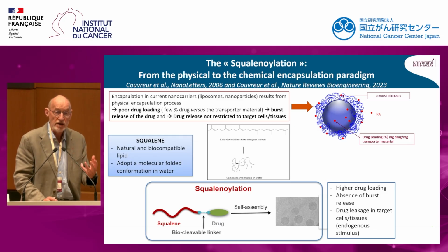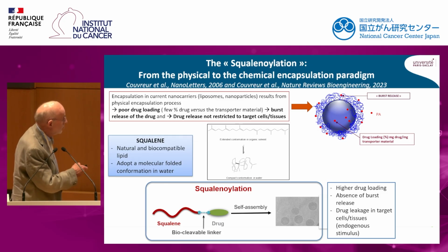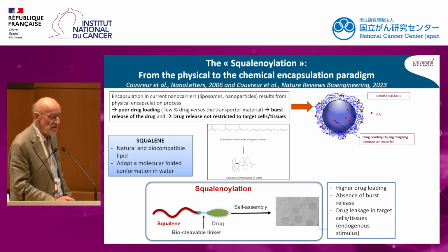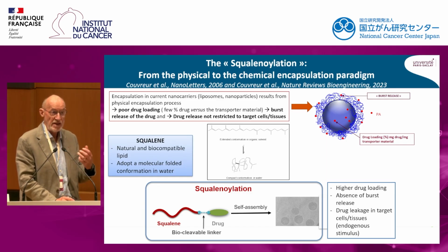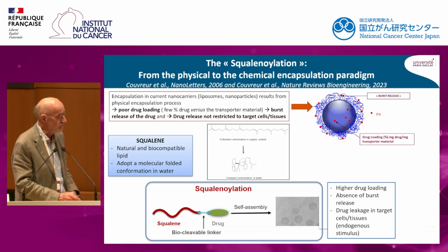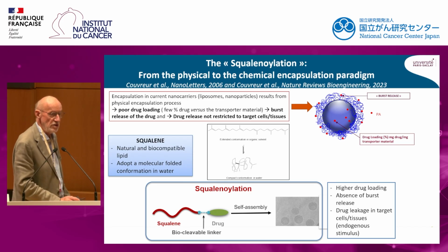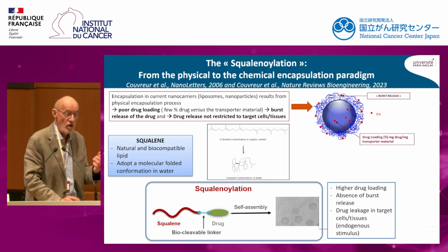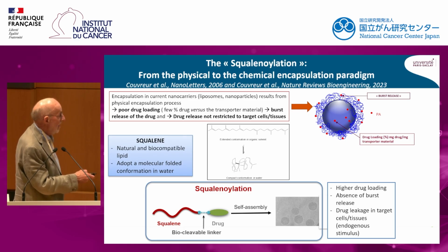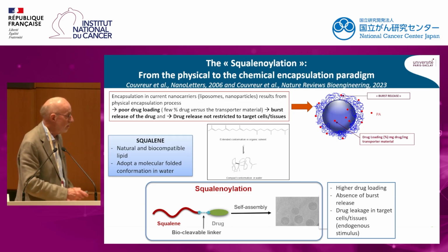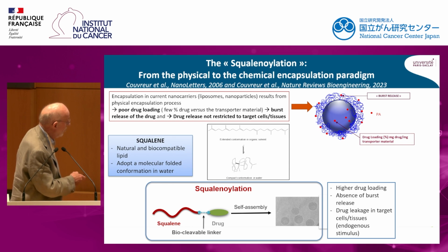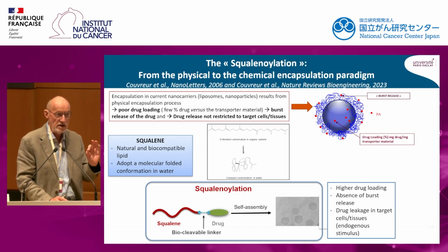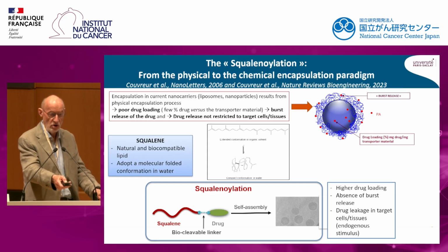And in fact, by supramolecular chemistry, when you put those prodrugs, those bioconjugates, into water, they will self-assemble as nanoparticles with a size of around 100 nanometers and with a much higher drug loading than after performing a physical encapsulation process, because as you can see here, each molecule of squalene will be able to transport at least one drug molecule. And also there is an absence of burst release because in blue you have a chemical link between the squalene and the drug. And if you are a good chemist, you can design a biocleavable linker which will be sensitive to an endogenous stimulus, allowing the drug liberation into the diseased cells or tissues.